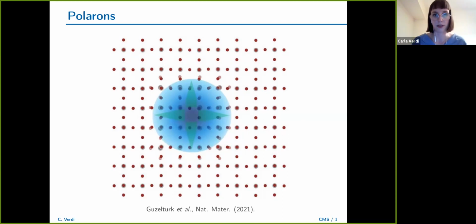So what happens is that when you take, ideally, a crystal, an insulator or a semiconductor, and you add an electron, this electron is not necessarily free. It moves around in the crystal, and it can induce a distortion in the lattice. The atoms that form the crystal lattice can actually move as well. And then the electron can get trapped by this polarization field that it induced itself. This is why it's called polaron self-trapping.